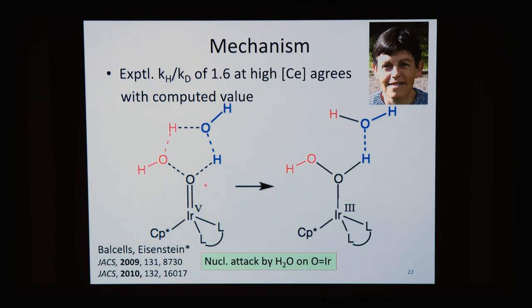So if we think of that oxygen as being O2 minus, then the nucleophilic attack of hydroxide becomes possible because the 2 minus are handed over to the iridium 5 to become iridium 3, a good leaving group. And the proton lost from the water, the red water, joins the bath, which is represented by the blue water, and the blue water gives up a proton to the other end of the molecule to give hydrogen peroxide. And once one has created the oxygen-oxygen bond, then there's no difficulty in moving on to oxygen itself, the dioxygen, I ought to call it.